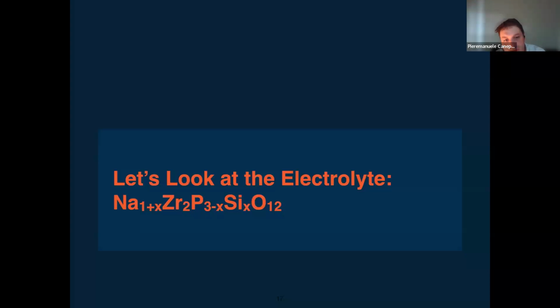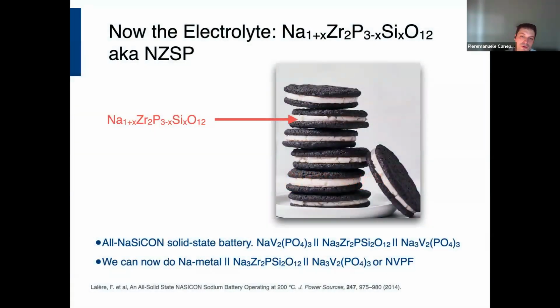Now, let me switch gear a little bit, and this is more about my research on the electrolyte side of this Nasicon material. Again, Nasicon is very versatile in terms of composition. Here we are looking at Nasicon where there is zirconium as the transition metal, so a closed shell transition metal. And depending on the sodium composition, you can have different phosphorus or silicon content, and you can have sodium vacancy availability or lack of sodium vacancy in this material. Again, bringing you back to the picture of the solid-state battery and the Oreo battery, we are talking about the filler in the Oreo biscuits that are depicted here.